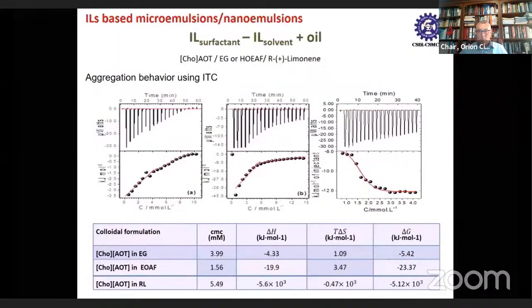Herein, we will be providing one example wherein we constructed microemulsions consisting of choline AOT based ionic liquid as a surfactant, ethylene glycol or hydroxyethyl ammonium formate as a polar medium, and a vegetable oil, R-limonene, as an oil phase. So initially we determined the aggregation behavior of choline AOT in ethylene glycol as well as in hydroxyethyl ammonium formate and in the oil phase. And if you can see the isothermal titration plots, it gives clear signatures where choline AOT is aggregated in the medium, and in non-polar medium, or one can say in limonene, this curve is different, but there is a clear aggregation of choline AOT in non-polar medium also.